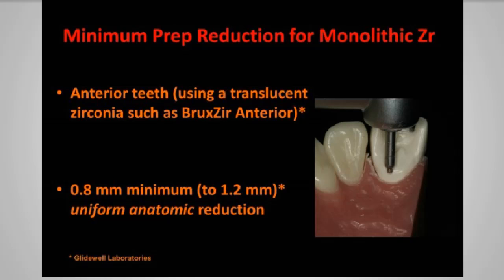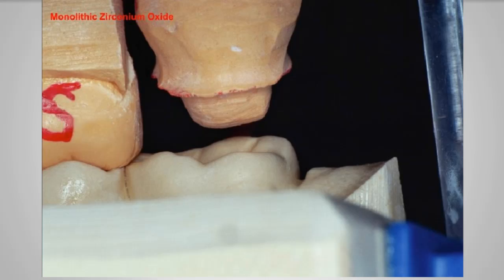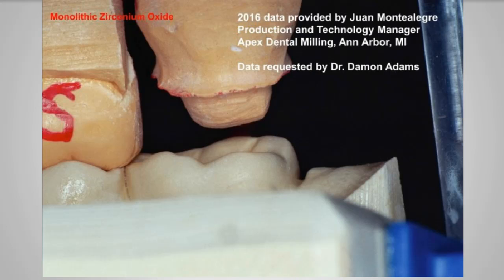And again, we want to make sure if you're in functional areas, you probably want to be approaching 1 millimeter, because reported again at Brigham Young University when I was lecturing with Gordon and Rella Christensen, they made a real point. Rella made a very good point that they're seeing fractures early on in translucent zirconia that's not thick enough in these functional areas. Again, a monolithic zirconia crown prep. Rounded line angles, much nicer looking prep, but too much room.